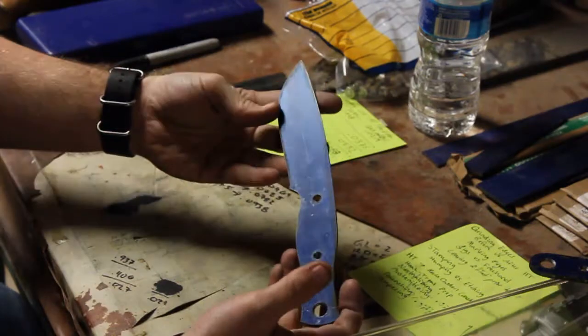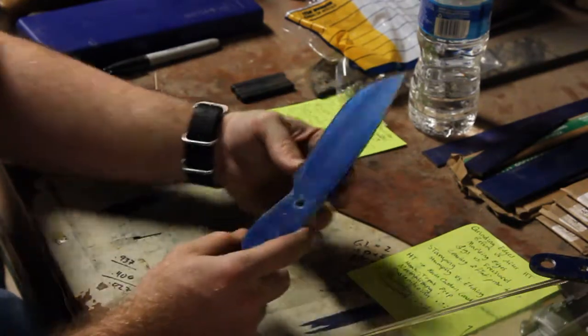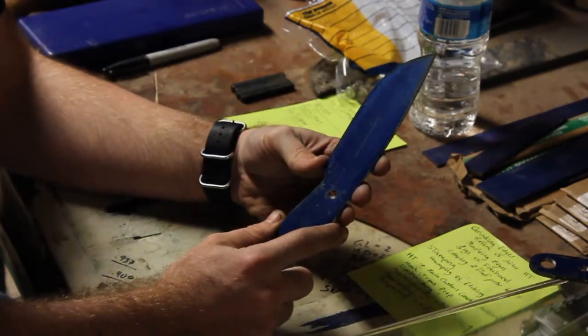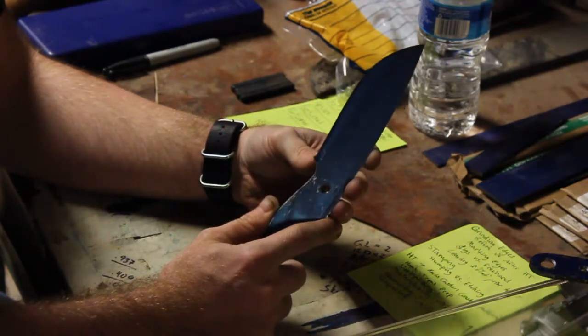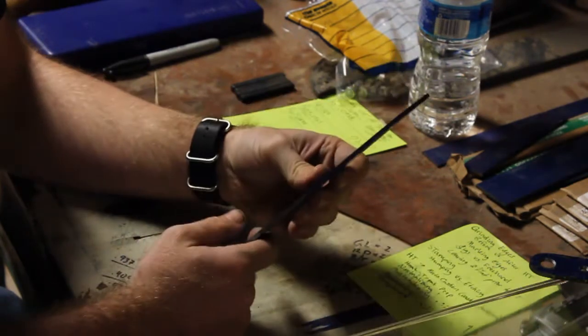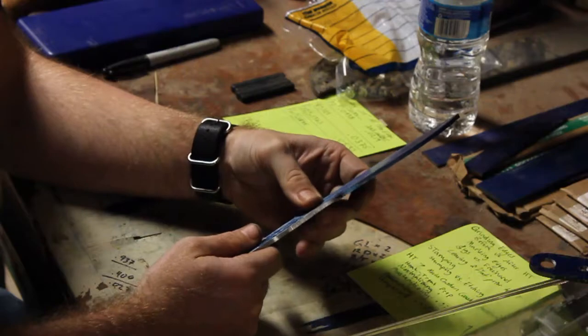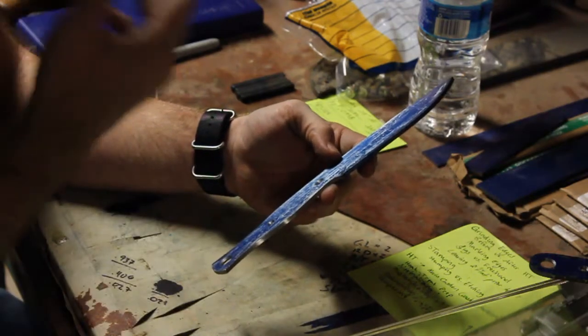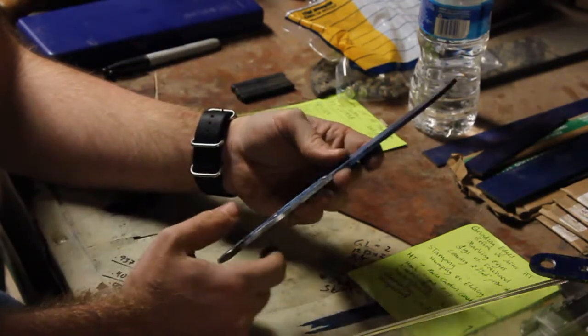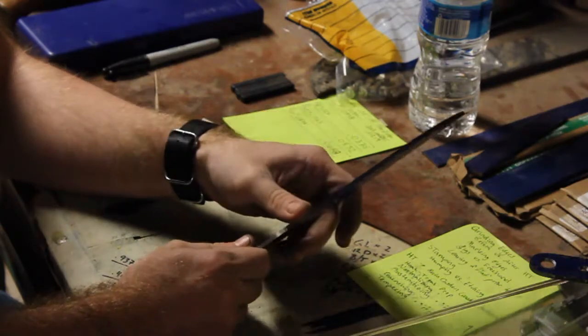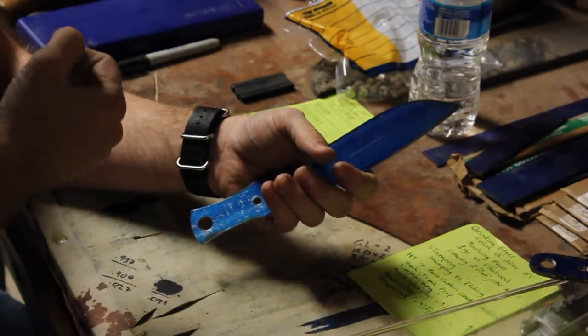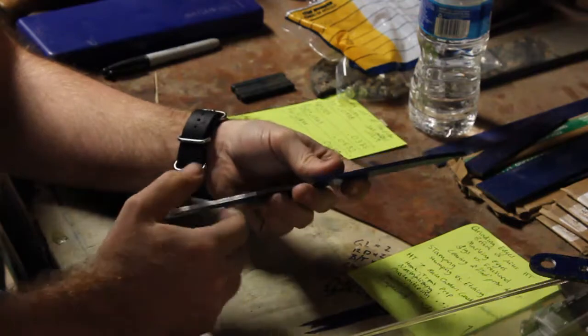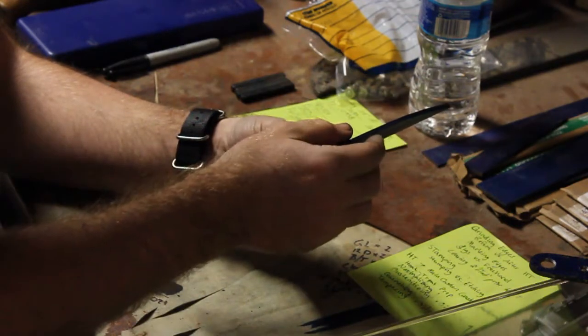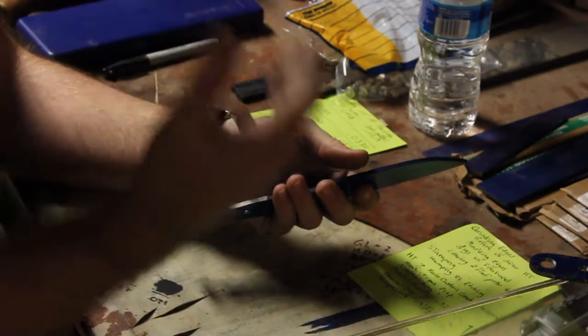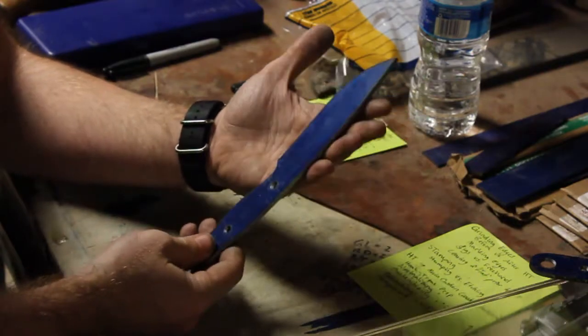Now we'll jump right into grinding the edges. I grind my edges before I heat treat my knives, and that's a preference thing. You don't have to do it that way. Some guys like to grind their edges after the heat treat, and that's fine, as long as you do it all correctly. Grinding your edges after you heat treat the knife, you're going to remove more material, and if you're not careful about it, you'll overheat your blade and you'll ruin the temper.